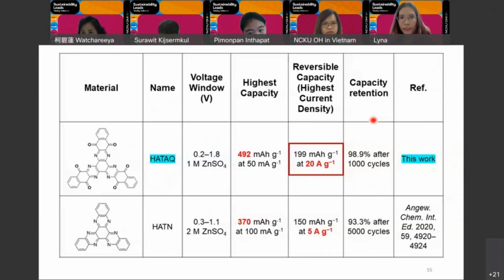And this table is comparing to the literature. HATAQ has shown the highest capacity at both high and low current density. Besides, it's also capable of very high current density at 20 amps per gram. Therefore, HATAQ material is considered to have the best electrochemical performance among HAT-based materials.